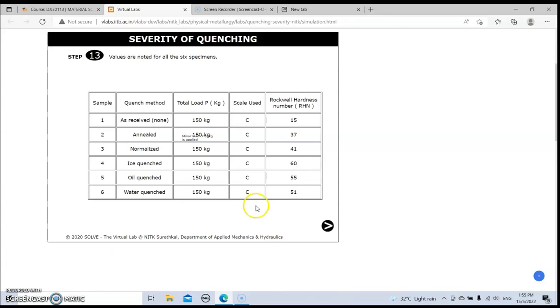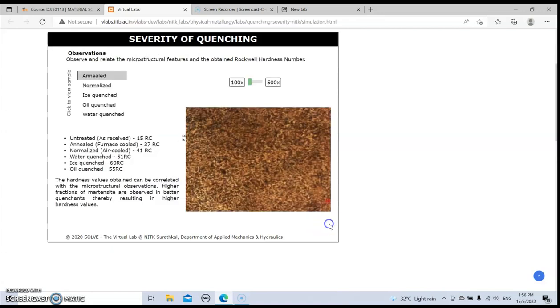Rockwell hardness number for sample 1 is 15, sample 2 is 37, sample 3 is 41, sample 4 is 60, sample 5 is 55, and sample 6 is 51. The hardness values obtained can be correlated with the microstructure observation. Higher fractions of martensite are observed in a more severe quench, resulting in higher hardness values.